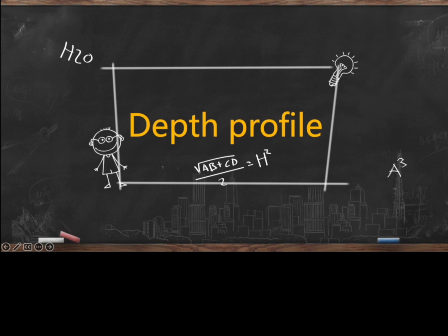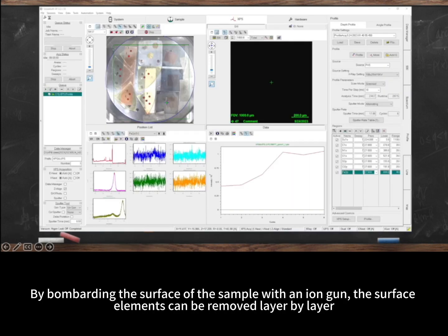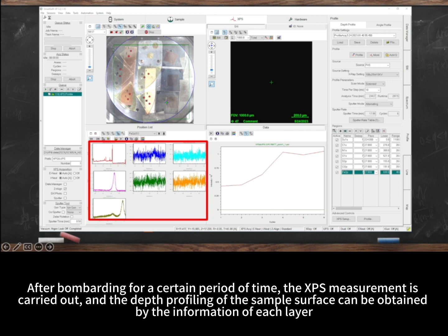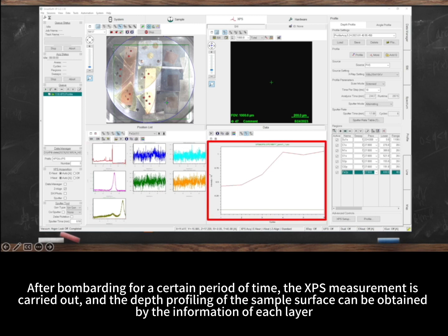Depth profile. By bombarding the surface of the sample with an ion gun, the surface elements can be removed layer by layer. After bombarding for a certain period of time, the XPS measurement is carried out, and the depth profile of the sample surface can be obtained from the information of each layer.